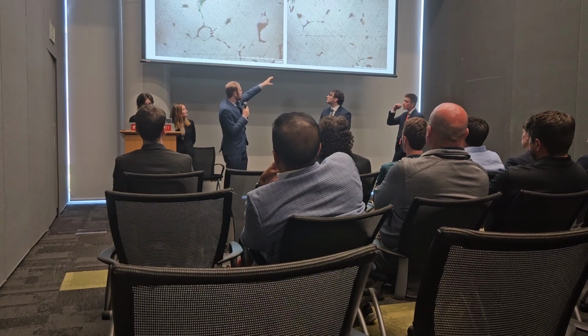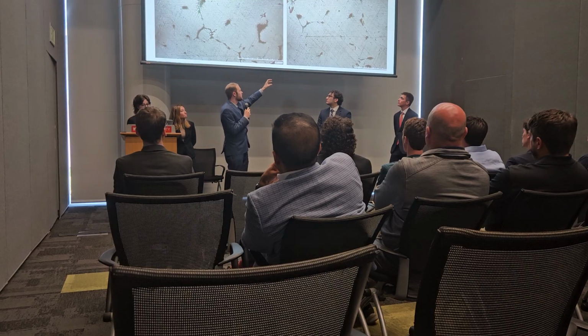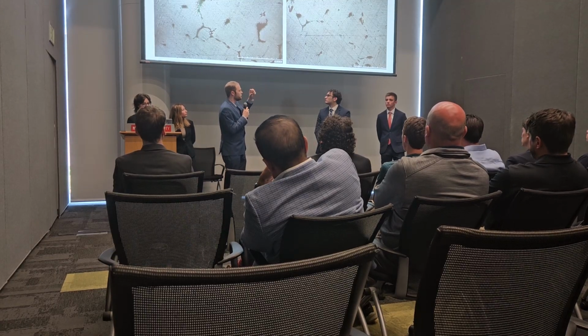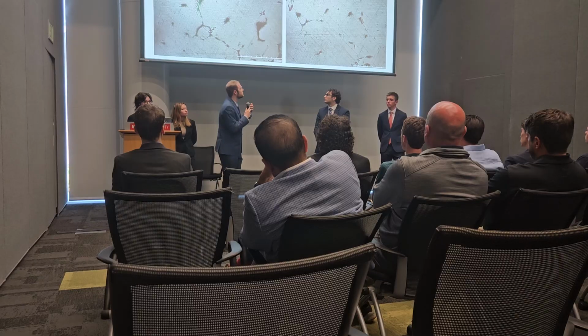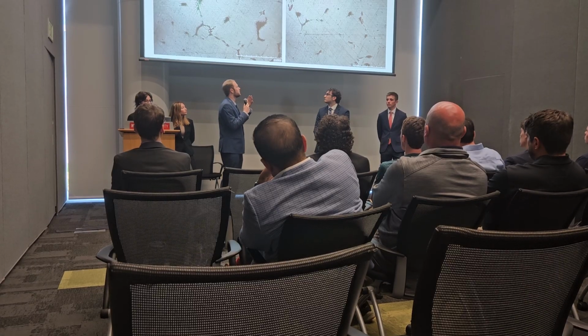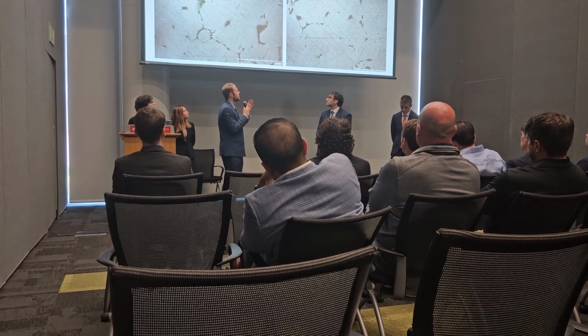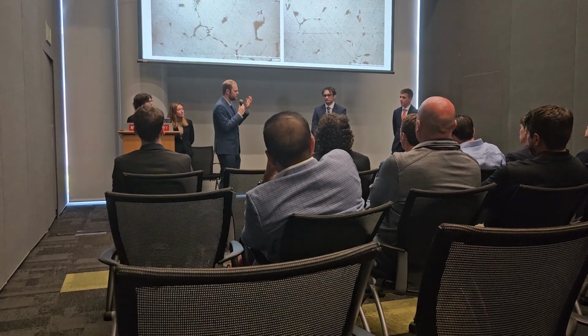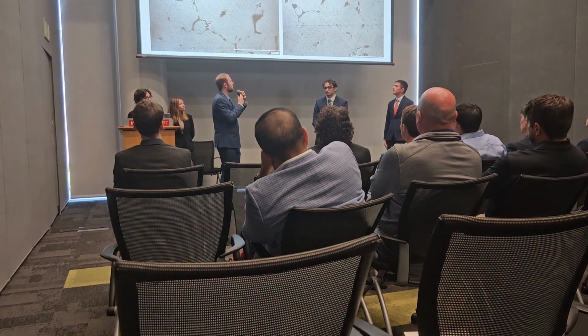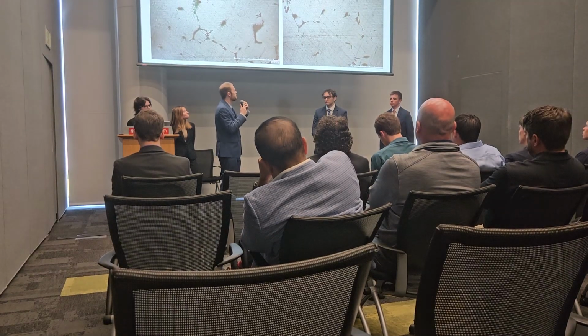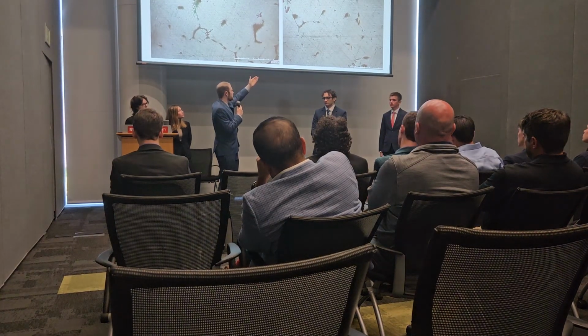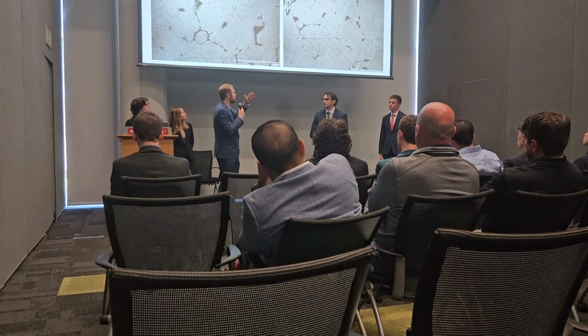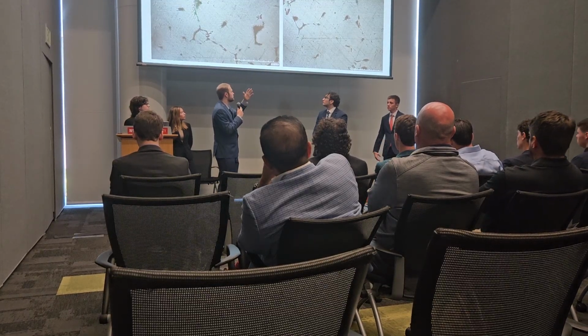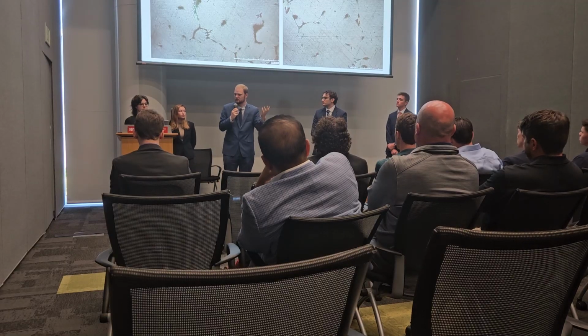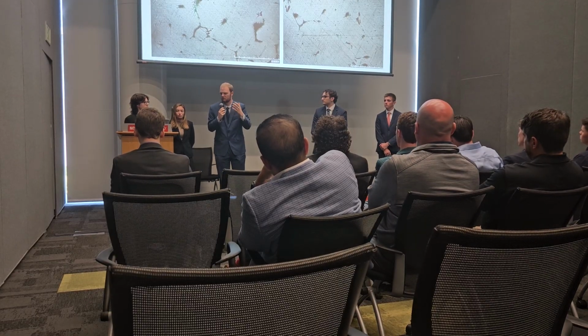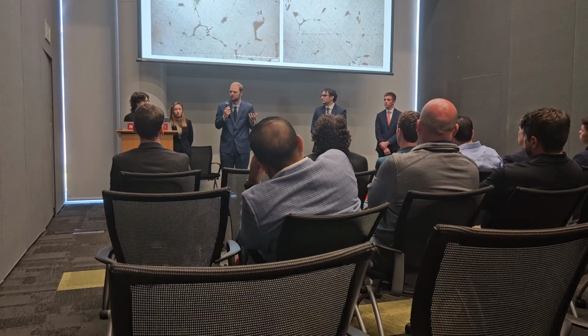This is the titanium carbide nanoparticles, which are meant to form along the grain's growth to allow for the microstructure to be more stable and to reduce hot cracking. Hot cracking happens when aluminum is cooling, the grains are converging on each other, and enough stress builds up that they pop. These titanium carbide nanoparticles are meant to flow along the edges of the microstructures and the grains to reduce that. And as we saw from our print, we didn't have any cracking, especially throughout our body, which meant the nanoparticles were successful in doing that.